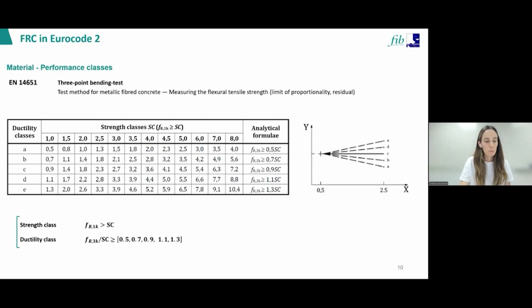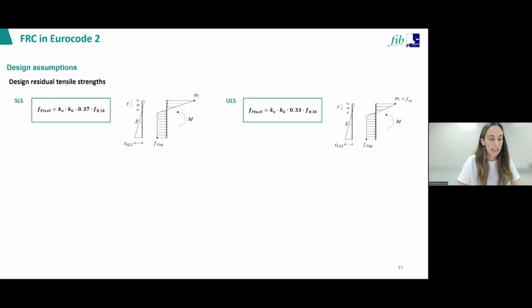after cracking. About design assumptions, since the material characterization is based on flexural tests, Annex L provides simplified approaches to derive equivalent uniaxial residual tensile strength for structural design. In this regard, two characteristic residual strengths are defined. One is associated with the serviceability limit states, another is associated with the ultimate limit states. These design residual strengths are obtained considering several correction factors, namely the fiber orientation factor and also the member